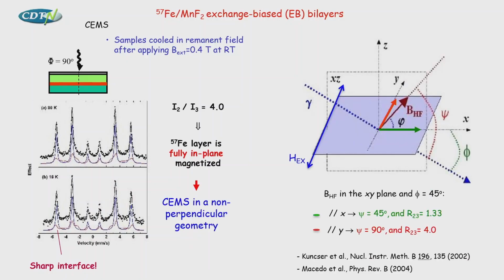Okay, and that means if you want to see some effect in the spins due to the coupling at the interface, you have to go to non-perpendicular measurements. They have to go to what we call CEMS in a non-perpendicular geometry. That means, because if you have the spins rotating in the sample plane, by measuring like this, you see that the angle between the gamma rays and the iron magnetic moment will change. That means then you are sensitive to change in the intensity of the lines.